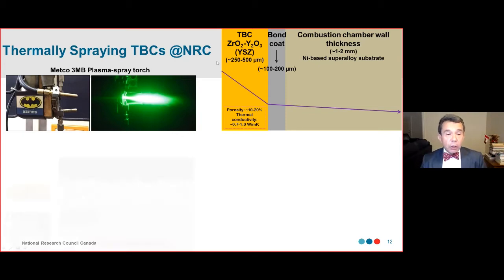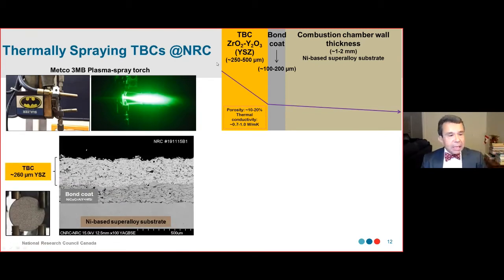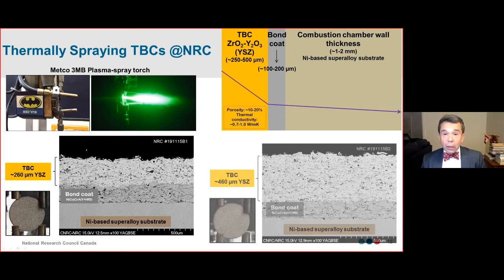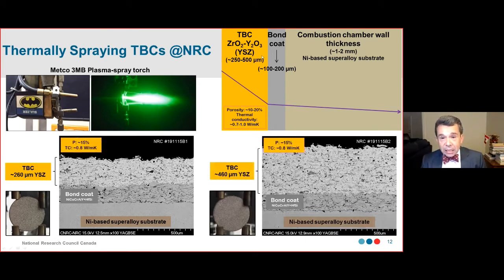So initially, I'm going to make a thinner TBC. It has a thickness of about 260, right? And then you have to make the same TBC but thicker. Okay, so make another one that's thicker. It's about 460, almost at the upper limit in here.